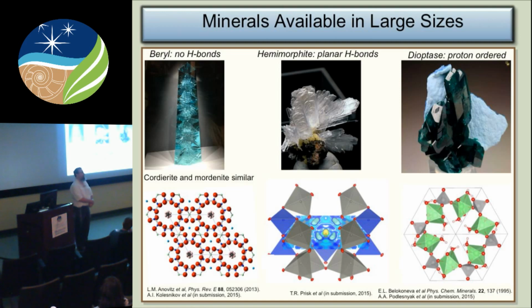Whereas in something like hemimorphite, which also has large channels, the water is bound in a plane to some of the oxygens around it. And in dioptase, we have a case where you have this big channel where the water actually makes up the end of an octahedron until you heat it. As you heat it, the dioptase changes first from green to blue, and the water appears to have just come loose, and we're changing the Jahn-Teller distortions around that octahedron. Heat it more, the water comes out, the coppers become square-planar, and you end up with completely either water-free or very mobile water in the material.